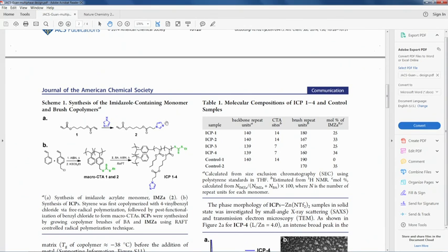At the end of it you have an imidazole moiety. If you take a certain ratio of butyl acrylate to a butyl acrylate which is functionalized with this imidazole moiety, then in that particular ratio they will add to the side chain in the RAFT polymerization. So, if here it is M and here it is N number of units, this M and N you can actually control by taking the monomer mixture in that particular ratio.